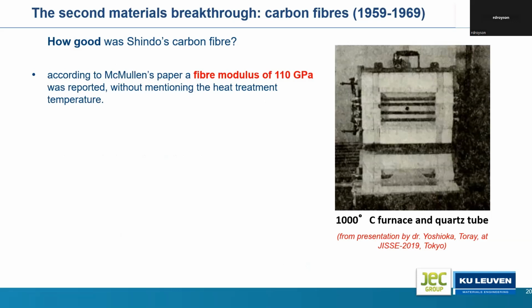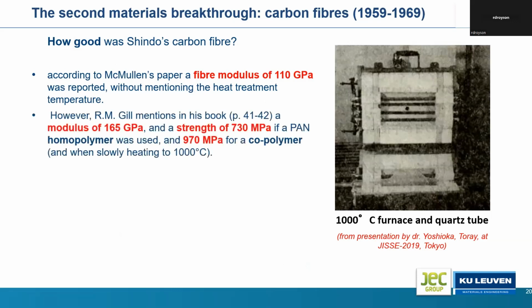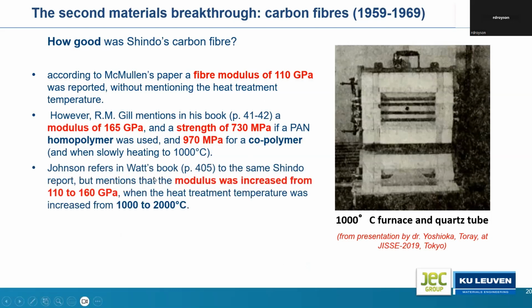Some people talk about a fiber modulus of 110 gigapascal. R.M. Gill, in his book, mentioned 165 gigapascal and a strength which, depending on the type of polymer used, was between 700 and almost 1000 megapascal. And then Johnson refers, in a book by Watt, that Shindo could increase the modulus of the carbon fiber from 110 to 160 gigapascal by increasing the carbonization temperature from 1000 to 2000 degrees C.